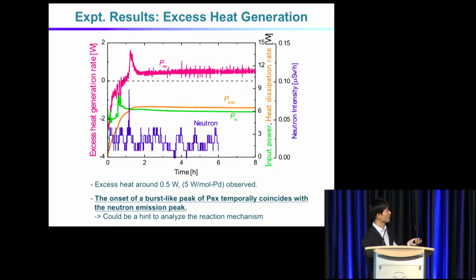And then we see some generation of excess heat, which was around 0.5 watt. And importantly, the peak of the excess heat temporarily coincides with the generation of the neutron signal, which could be a hint to analyze the reaction mechanism. And we are going to go into the details in the future.